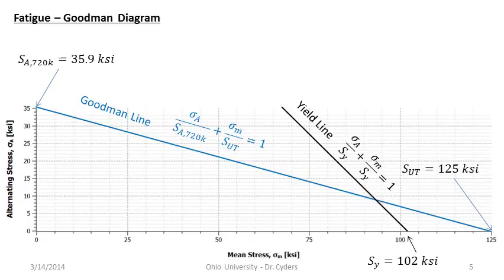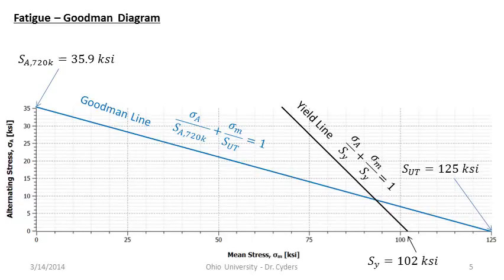The SN diagram itself is based on noisy data — notoriously variable. Even when plotted log-log, the noise is visible and the fits aren't great. We have to understand that these models are stochastic in nature with a lot of variability. This isn't derived from first principles like the second law of thermodynamics — it's not hard and fast and deterministic. We use it as a tool to determine our distance from the failure envelope, understanding that a factor of safety accounts for variability and unknowns we can't otherwise predict.